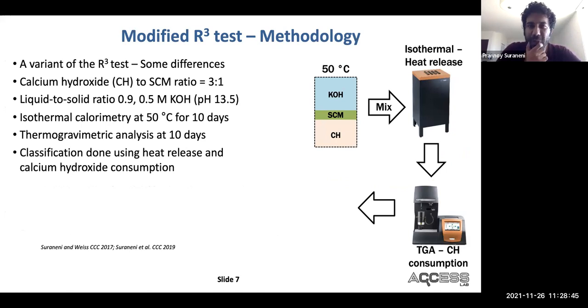It's a variant of the original R3 test, which was developed by Professor Karen Scrivener and several others. What we're doing is we're taking a 3:1 mass ratio of calcium hydroxide and SCM. The liquid to solid ratio is 0.9. The solution is a 0.5 molar potassium hydroxide solution, which brings the pH up to 13.5. We run isothermal calorimetry at 50 degrees for 10 days, and then thermogravimetric analysis at 10 days.